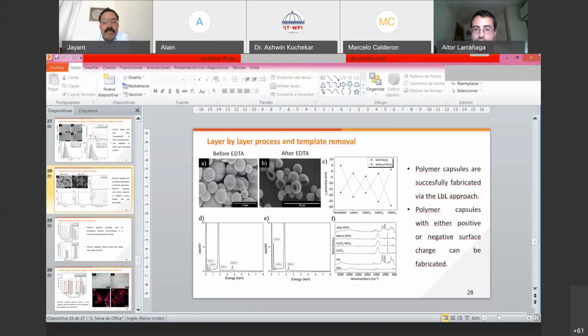But Marcelo was asking, maybe that's what I understood, where would your Mn be? Will it be on the surface with the calcium carbonate template? Well, the calcium carbonate template is removed, right? Okay. I imagine for that I could tag the manganese dioxide with some fluorescently labeled molecule or try to do some TEM that we didn't do in this project. But I believe it will be within the polymer capsule, but attached to the inner cavity because of the electrostatic interaction. You have to think that manganese dioxide is positively charged and the next layer will be negatively charged. So there might be some kind of interaction, but this is something that we could check by TEM, for example.